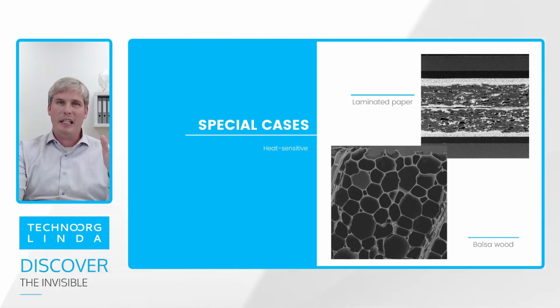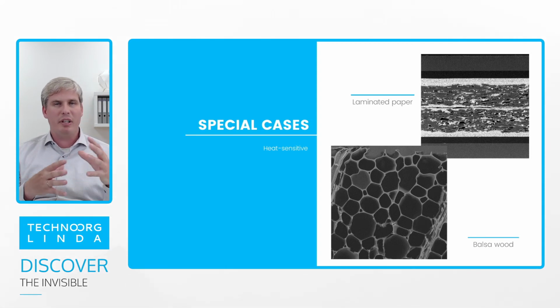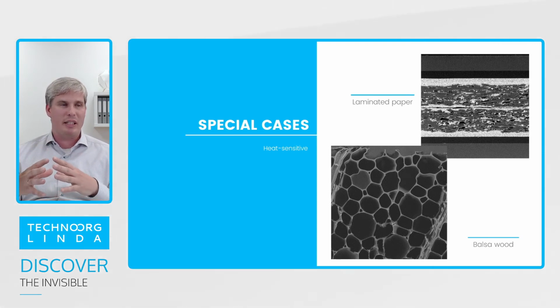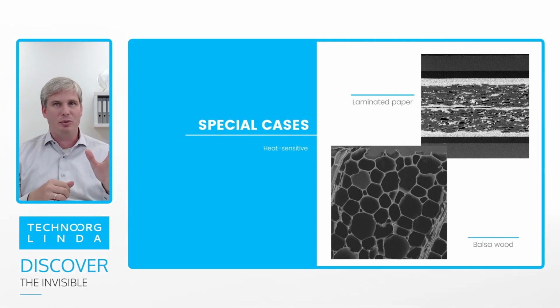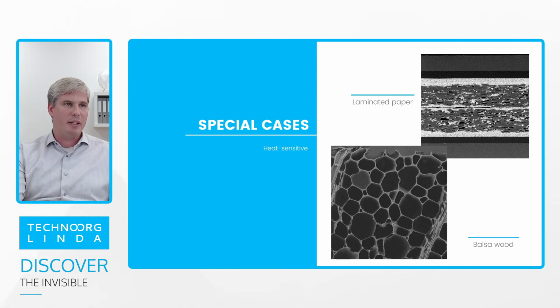So here, I'd like to show you that even in the very heat-sensitive cases, there is a solution. Here you see a balsa wood, but it's a very delicate sample. It has a special inner structure, and thanks to this structure, the balsa wood is very light but extremely strong at the same time. And this inner structure can be observed only if you have the right approach and the right recipe, and also the right devices to make it, because it's absolutely easy to destroy it or burn the whole area. The laminated paper is very similar, but you can see that a great result is achievable.